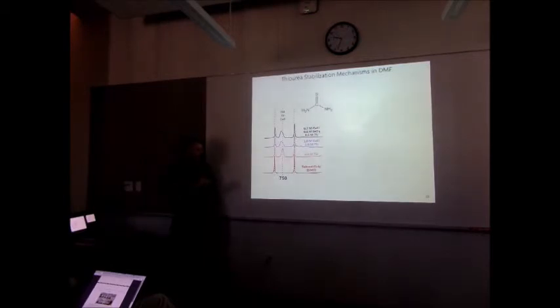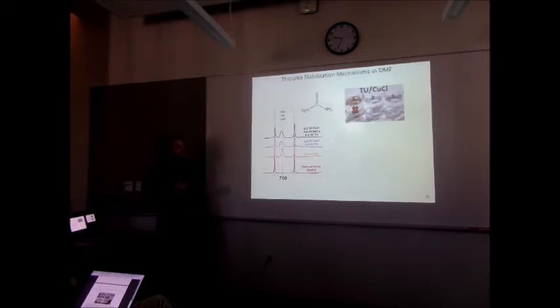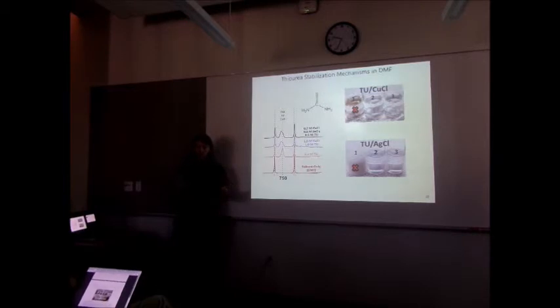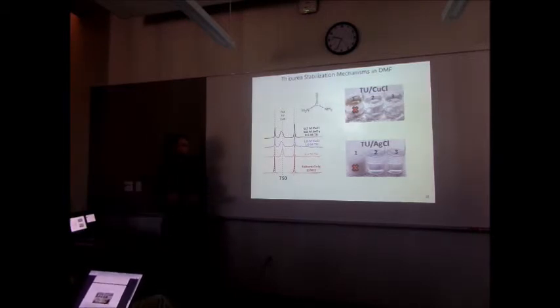And in the case of thiourea alone, the peak perfectly lines up with theory. But when you look at copper chloride in solution, you can see this shift in the peak. So copper chloride is coordinating with this Lewis basic site in solution, and this leads to its stabilization. If you don't have any thiourea in solution, it's unstable, but in a 2-to-1 ratio, 2 thioureas will come in, complex it in solution and stabilize it. Additionally, we were able to show this with silver chloride as well. So now we have all the tools we need to do the germanium and silver coalloying, as I mentioned.